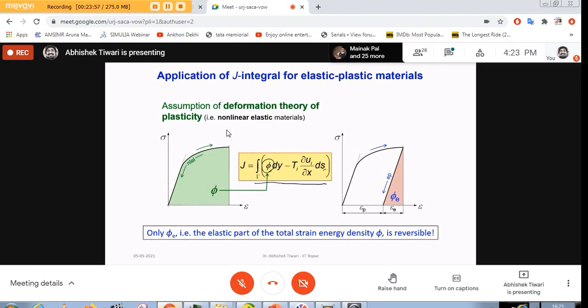But because J integral assumes this material to be non-linear elastic, it takes the whole area under the stress strain curve. But only this part of an elastic plastic material is available for the crack to grow. So if you have to take it, then you should only take strain energy density or elastic strain energy density. But in that case, the definition of J integral will face a lot of problems.